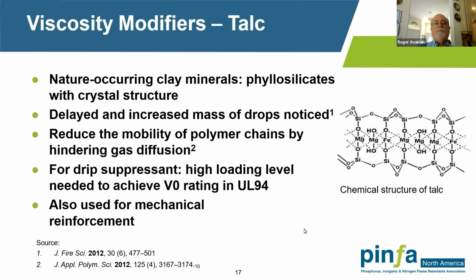Next slide. I mentioned viscosity modifiers, talc being one. It's a naturally occurring clay mineral. You can see the chemical structure for this. It's a plate-like, platelet material. Basically, you can see the references here: delayed and increased the mass of drops noticed. So the key thing was delaying it and making sure there were not a bunch of small masses of drops. Again, I might point out that not all talcs are created equal. There are some materials that work better than others.